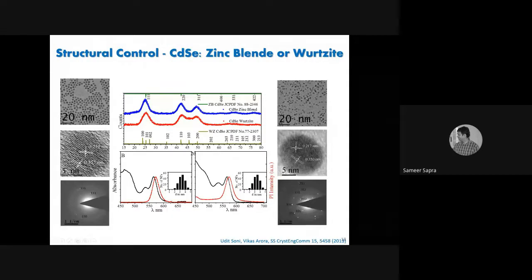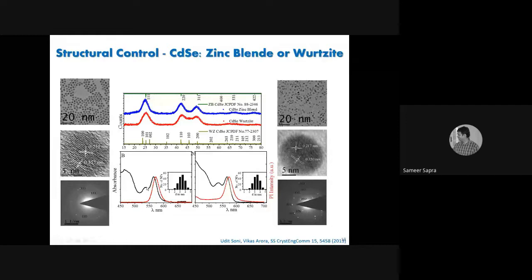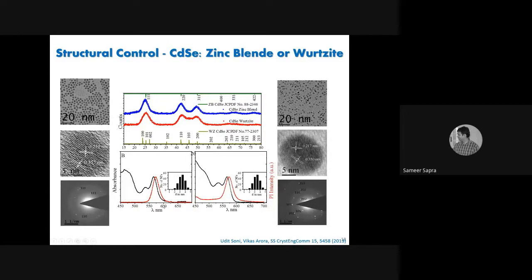Also, you need to characterize these particles by means of spectroscopy, particularly UV-vis absorption spectroscopy. You can see all the excitonic features, the first, the second, the third, and people have even observed up to 7 excitons. So these are all visible, though we have to go to higher energies, lower wavelengths, of course. Then the good thing about some of them is they are also fluorescent, so they give you emission. And these emissions are what I showed you. For example, this one is roughly about 575, so it would be yellowish in color, greenish yellowish, more towards yellow.